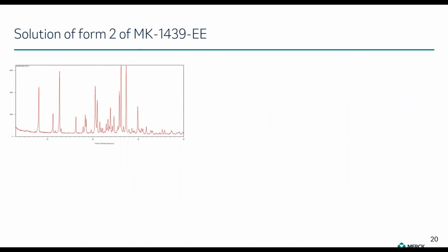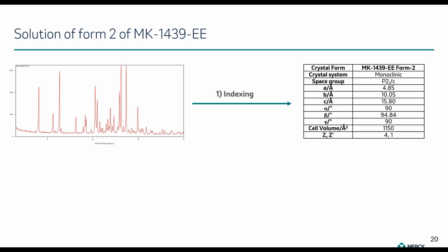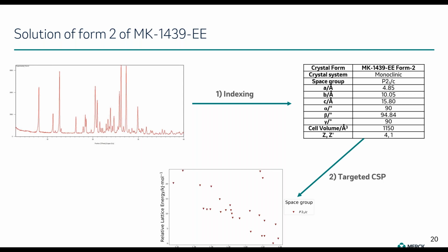So starting from the powder X-ray diffraction data, we performed indexing. We basically determined the unit cell dimensions and the space group, and this was confirmed by Pawley refinement. Then we performed a very targeted CSP that was limited to the P21/c space group and unit cell dimensions very close to those from the indexing. And as a final step, we compared the crystal structures that we generated to the experimental powder pattern to see if the simulated powder pattern of any of them matched the experimental powder pattern, and this was done with a cross-correlation function method.